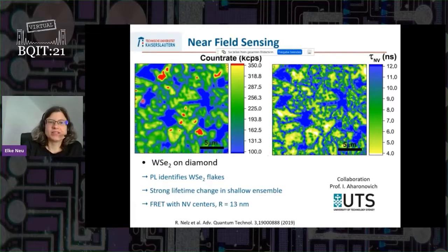So if you look first at the sample, you see areas with very bright luminescence, the green yellowish ones here. You can see already here the triangular shape, for example. So these very bright areas are the tungsten diselenide flakes. The weaker fluorescence in between is the fluorescence of this layer of the NV centers.